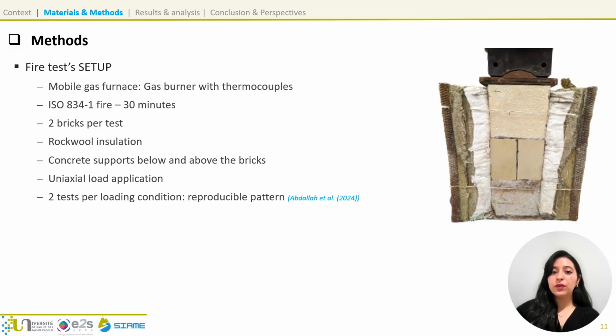Each test involved two bricks placed between concrete supports with rock wool insulation on the sides to reproduce uniaxial heat and water transfer, similar to what happens in real walls. A uniaxial load was applied during heating to simulate structural conditions.